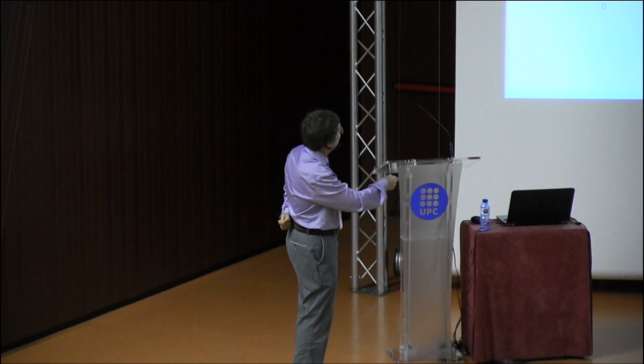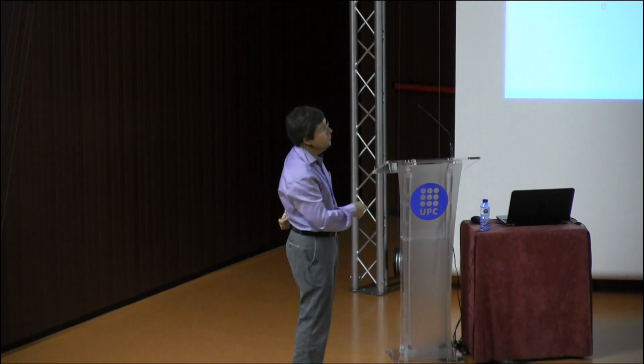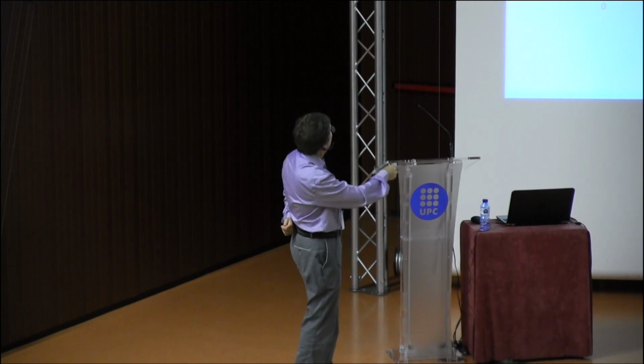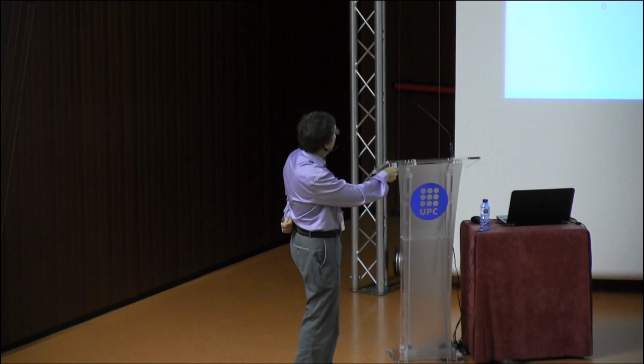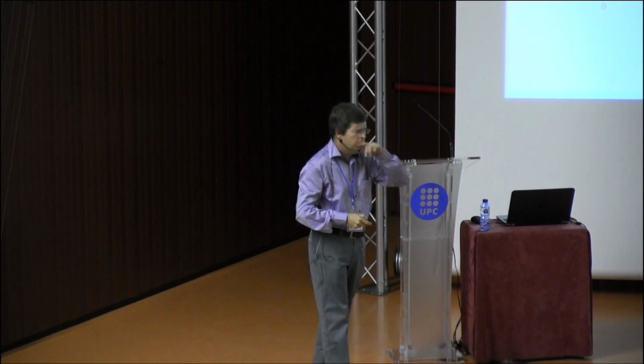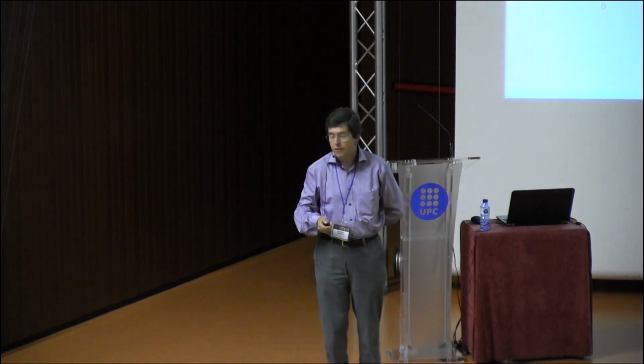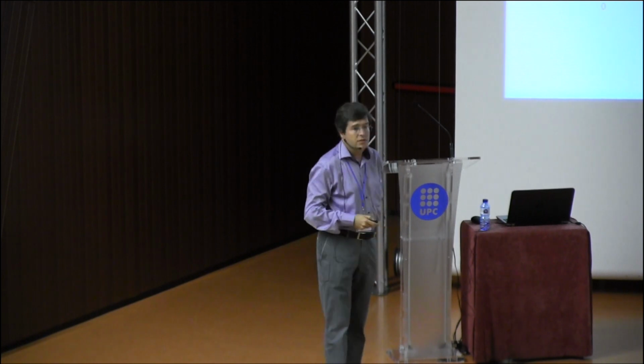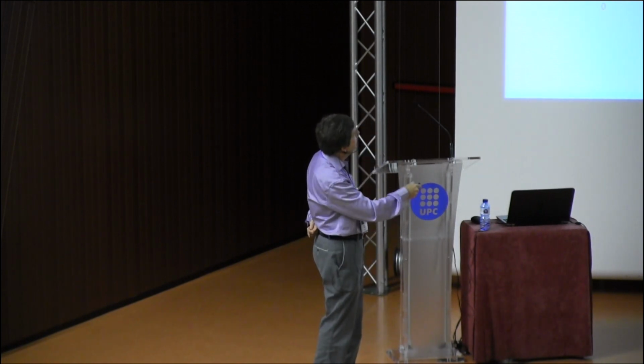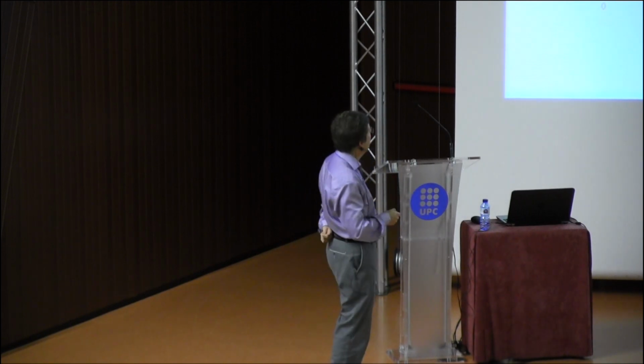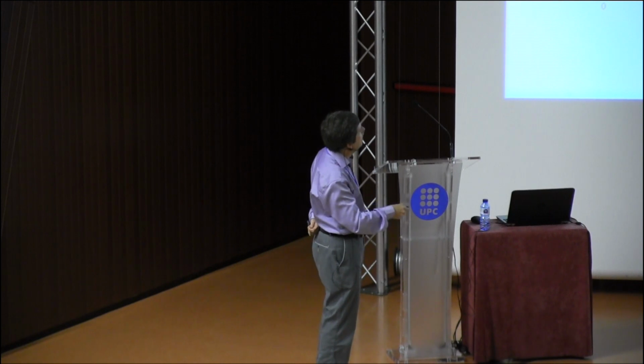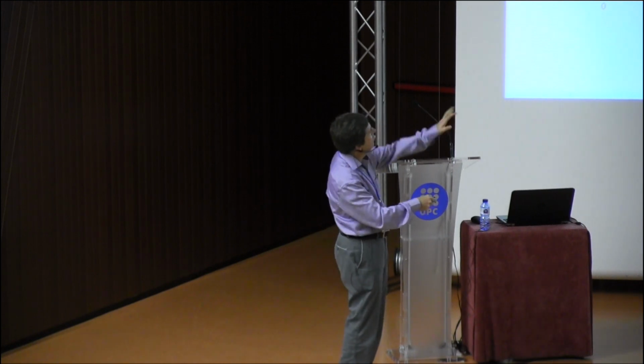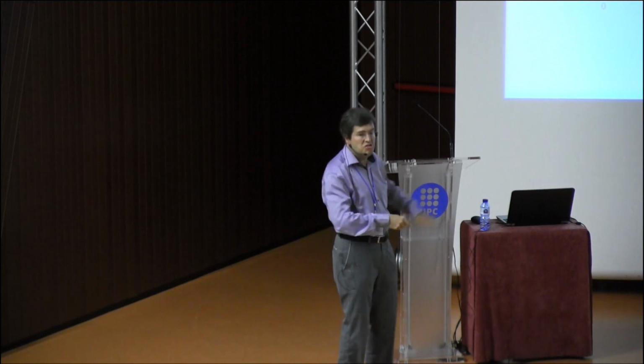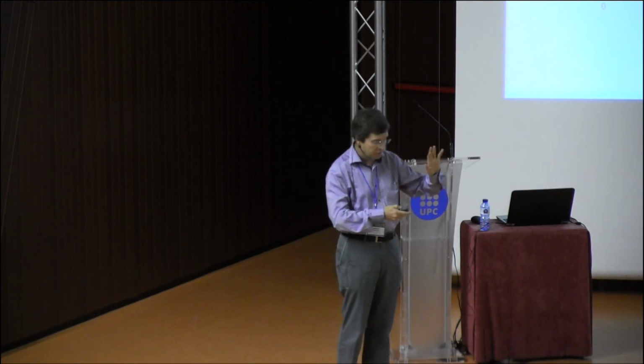If you compute on a volume element, you get this constitutive curve. But if you compute on a sample like this, you will have a stress drop and then a plateau. People usually don't really care about the mesh of the finite element method they are using, because they think the hardening at the end will prevent mesh dependence. But if you look more carefully, with a regular mesh or a random mesh, the plateau is already a bit ugly and not really reproducible.